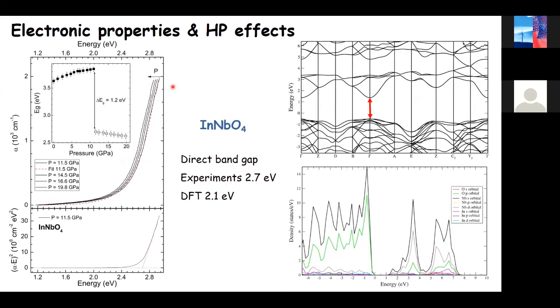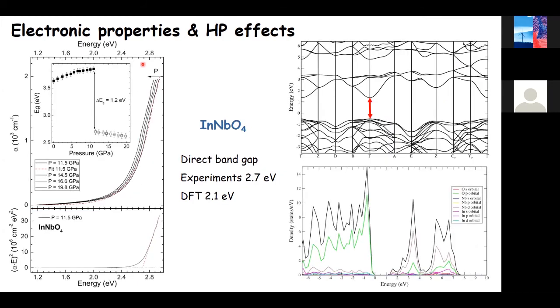If you go to the indium niobate, I'm sorry. First, I will go to the high pressure phase. The high pressure phase is a direct band gap material. And again, we observe a collapse of the band gap due to the change of the coordination of the niobium, which goes from values around 4 eV to values around 2.8 eV. It's not as big as in indium vanadate, but it's 1.2 eV.